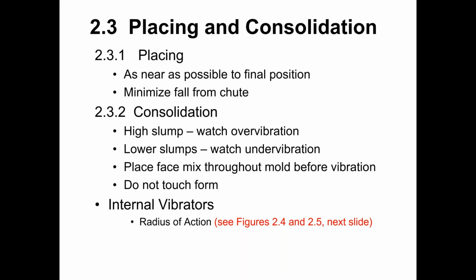Also, we want to make sure that if we are placing the precast unit in multiple lifts of concrete, that the internal vibrator penetrates the current lift that's being cast and goes into the previous lift so that we get good consolidation across that boundary layer between the two lifts of concrete. We don't end up with a cold joint at that location.